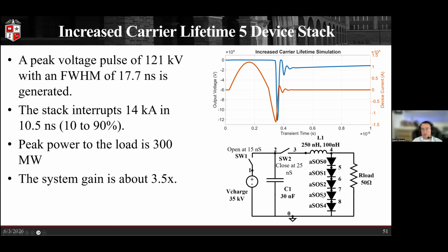One of the caveats to note on this simulation is we are using multiple strings in parallel, not just the 5 devices in series. So we wanted to increase the overall active area, and so we end up with 10 strings in parallel of 5 devices. So it was 50 devices. By contrast, in the earlier simulations, we were only using 5 devices.